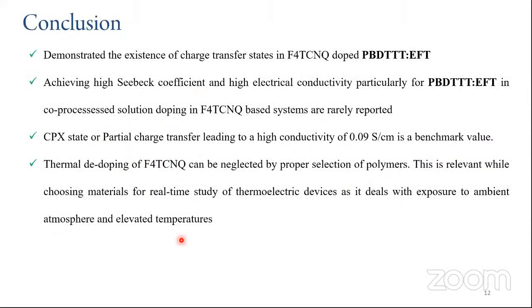In conclusion, we demonstrated the existence of charge transfer states in F4TCNQ doped PBDTTT, achieving a high Seebeck coefficient and high electrical conductivity, particularly for PBDTTT in solution processing, is rarely reported. And the charge transfer complex state leading to a high conductivity of 0.09 Siemens per centimeter is a benchmark value, and thermal de-doping of F4TCNQ can be neglected by proper selection of polymers, and this is relevant while choosing materials for real-time study of thermoelectric devices, as it deals with always an exposure to ambient atmosphere and also elevated temperatures.